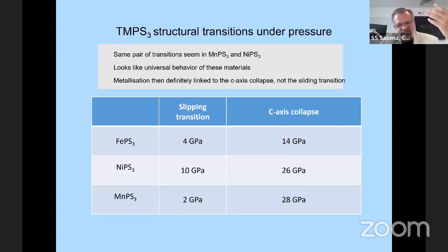But let's keep to what we have published. We're following up this work on FePS3, where we see the c-axis collapse, which completes around 14 GPa, with NiPS3 and MnPS3. In these materials we find this new kind of magnetic order, a new magnetic metal emerging at high pressures. Now the job is to see what kind of quantum states we can characterize in these areas. We're using all the tools, both resistivity and magnetization. Unfortunately, at such high pressures we cannot do heat capacity, which would be very useful, but it's a thing to develop. And again, if people have ideas about that, we'd be very happy to discuss collaborations.